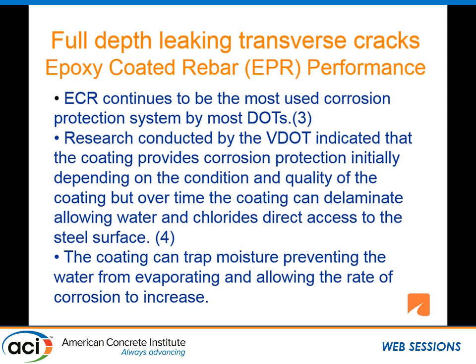Epoxy-coated rebar continues to be the most used corrosion protection system by most DOTs. Research that we did in Virginia, and Richard Weyers was the leader in all of the research we did on epoxy-coated rebar, shows that the coating provides corrosion protection initially, depending upon the condition of the coating and the quality of the coating. But over time, the coating deteriorates and delaminates, allowing water and chlorides direct access to the steel surface. This coating can actually trap moisture, preventing the water from evaporating and allowing the rate of corrosion to increase.